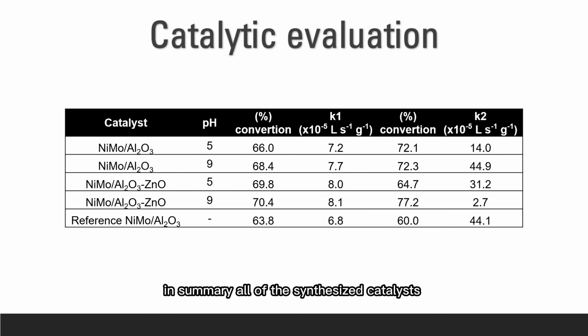In summary, all of the synthesized catalysts show higher catalytic hydroconversion of triglycerides with respect to the reference catalyst. The most active catalyst of this series is the nickel molybdenum alumina zinc oxide impregnated at pH 9.